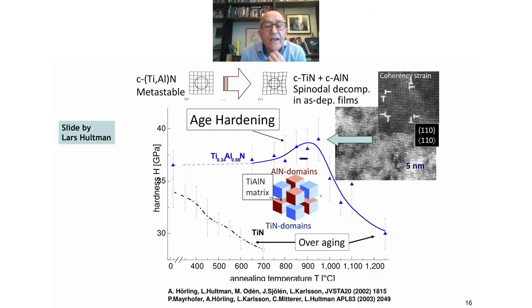Next slide. Now, another characteristic of titanium aluminum nitride that I would like to introduce is, if you look at the lower curve, titanium nitride, if we anneal titanium nitride, these stresses that have been introduced by ion bombardment tend to anneal out. The hardness usually drops as argon diffuses out and stresses are removed. Titanium aluminum nitride actually hardens. If you look at the schematic up in the picture, the as-deposited film has a random distribution of titanium and aluminum, and the lattice is close to strain free.